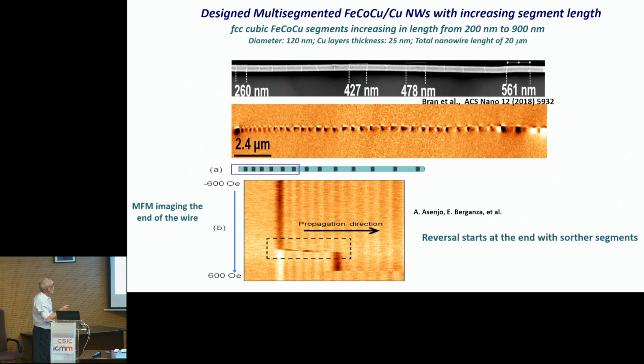And the last experiment I wanted to mention is these magnetic nanowires separated by copper segments. You see the white lines correspond to the copper, and these copper segments are separating ferromagnetic segments. But interestingly, the nanowire was designed so that in one end of the nanowire, the length of these ferromagnetic segments is much smaller than in the other end. So the length of the segments increases from one end to the other.